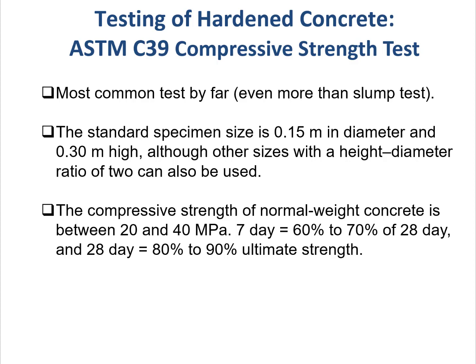The compressive strength of normal weight concrete measured by this test is often between 20 to 40 MPa. The 7-day strength, which means the compressive strength measured after 7 days of curing, is approximately 60% to 70% of the strength after 28 days of curing. And the strength after 28 days of curing is approximately 80% to 90% of the ultimate strength.